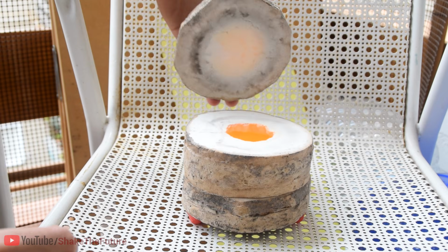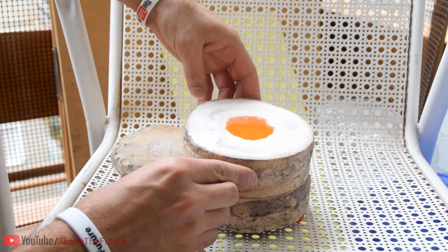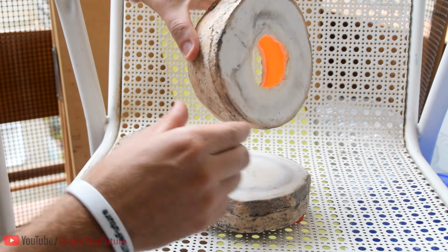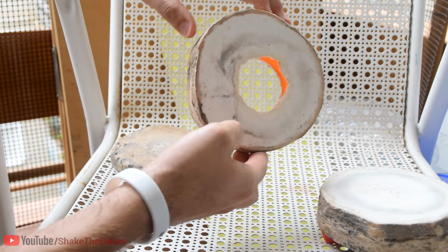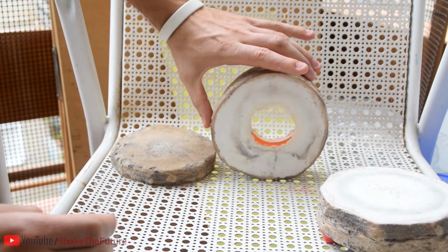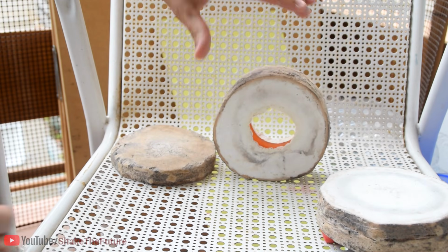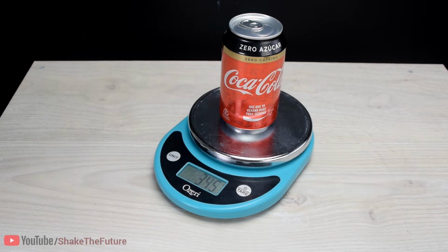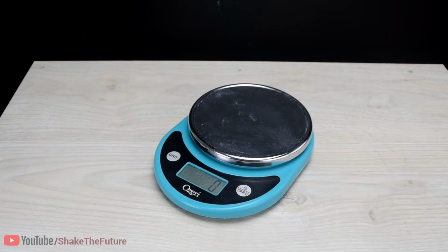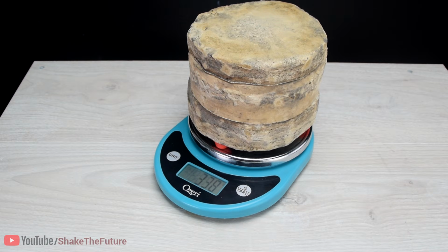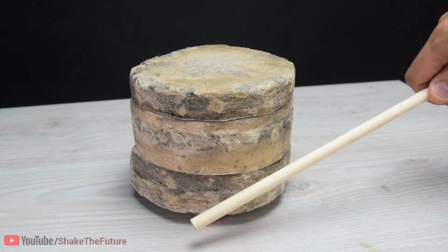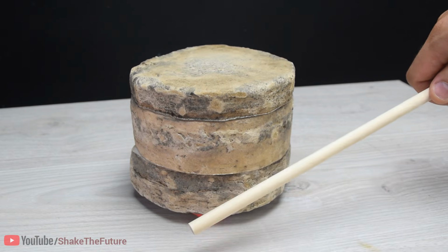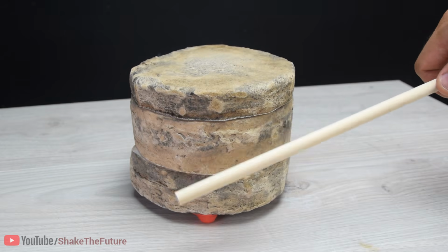This kiln is made differently. If you made a mistake and you want to cool the kiln as fast as you can, just flip it on its side while it's still hot and it's not going to crack. Because of ceramic fiber and water glass, the kiln weighs less than a can of Coke. And the water glass, it's pretty hard.